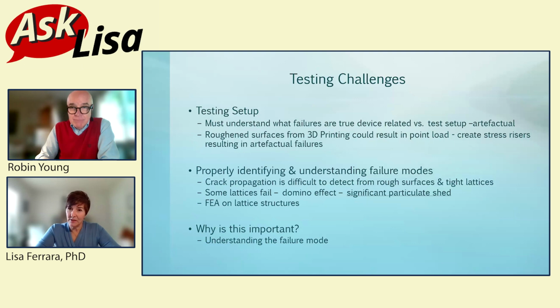There's many testing challenges. You have to think this is not conventional titanium implants where you get tight, repeatable data. Now, we're getting much better at it, obviously. How far are we out? 10 years out? When we started testing, we were one of the first companies to test these printed devices. And the failure modes, understanding the failure modes, are very different than machine repeatable implants.